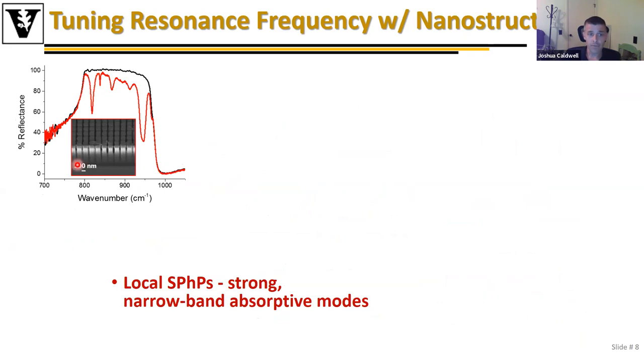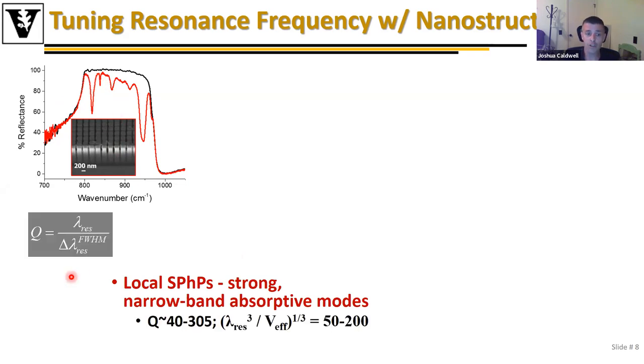And this is enabled by these phonon polaritons, which if I make these structures, for instance, these are some of the original structures we made in collaboration with Stefan Maier's group, where you can see these roughly 200 nanometer structures fabricated into a silicon carbide substrate, gives rise to these very narrow thermal emission, absorption bands within the Reststrahlen band of silicon carbide, which can have exceptionally large Q factors. In our work, we were able to show up to about 300. More recent work from Federico Capasso's group has shown that you can get this extended up to about 400, and now with Sang-Hyun Oh, approaching 500 quality factors for quantum polariton modes.